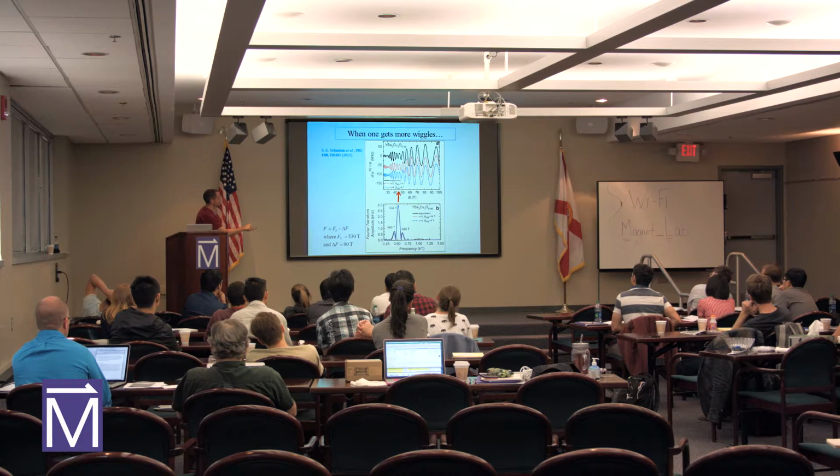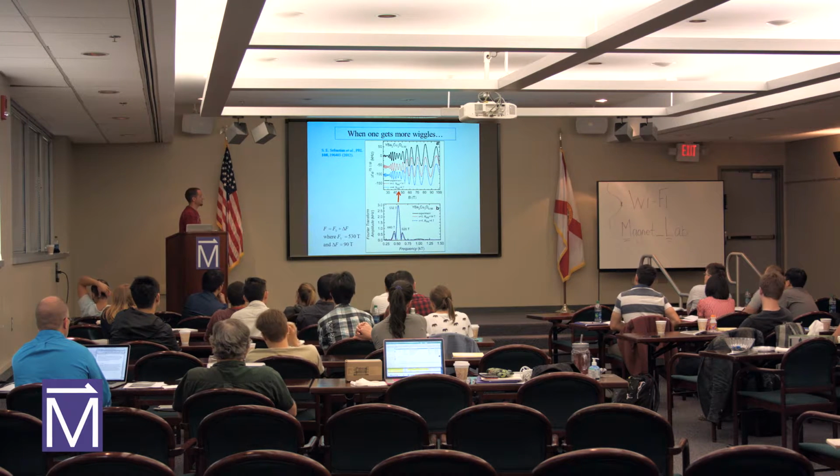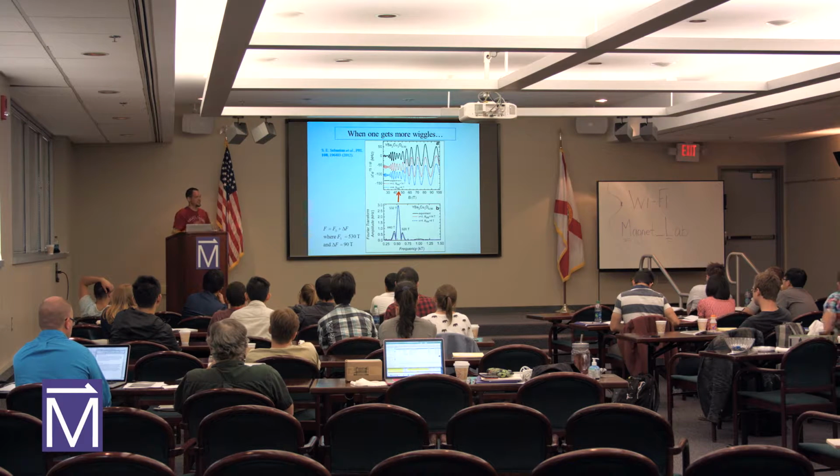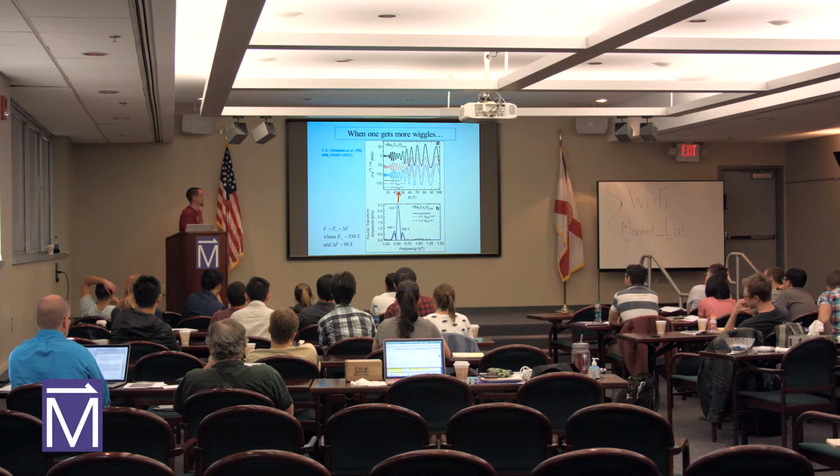And when she FFTs the data, there are 3 distinct peaks that show there should be 3 different orbits to the material. I think you'll see a film at some point during the week about the pulsed field facility in Los Alamos. We can't do all the same measurements we do here in Los Alamos. There are some drawbacks to being able to get to 100 Tesla. You have to do your whole experiment in tens of milliseconds, so that can be difficult.